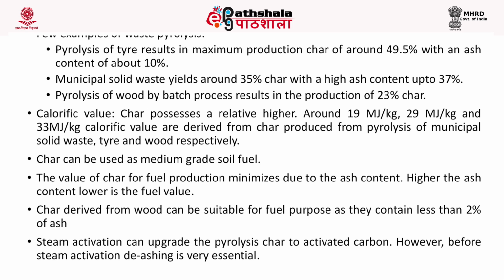Now, if you look into the calorific value, char possesses a relatively higher calorific value. Around 19 megajoules per kg, 29 megajoules per kg and 33 megajoules per kg calorific value can be derived from char that is produced from municipal solid waste, tire and wood. Char can be used as a medium grade solid fuel. The value of char for fuel production minimizes due to the ash content. That means the higher the ash content, the lower the fuel value. Char that is derived from wood can be suitable for fuel purposes as it contains very little ash, that is 2%.